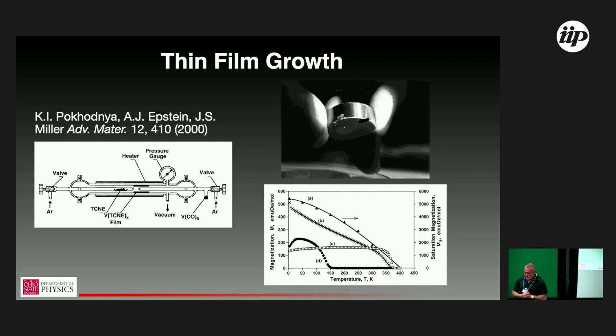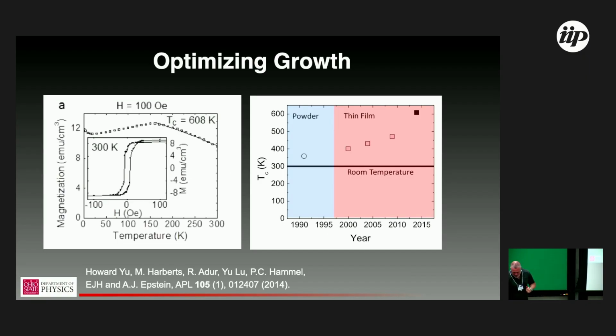Actually, I think in the next slide, so I'll just do that. So this is work that my group started in collaboration with Arts in optimizing this thin film process. And you can see the M versus T looks quite different in the more optimized film. And here I'm quoting a Curie temperature of 600 Kelvin. So we can't measure the sample anywhere close to 600 Kelvin without it turning into soot.